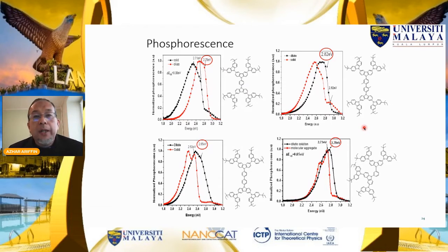because we can functionalize the carbazole and at the same time maintain the molecule at a high level of triplet energy. In OLED study, one of the important criteria is to have the molecule at high triplet energy. This is in order to get blue light from the OLED device.